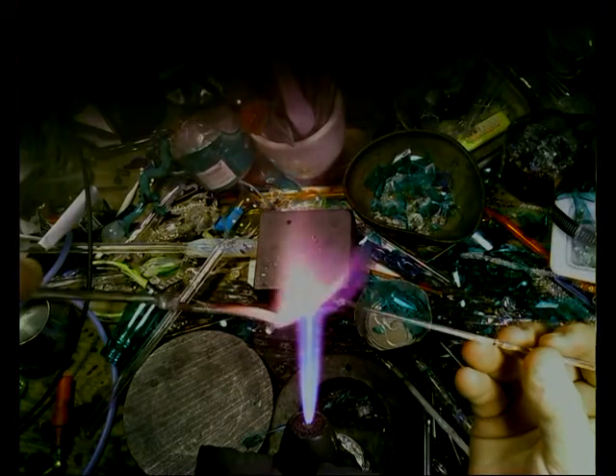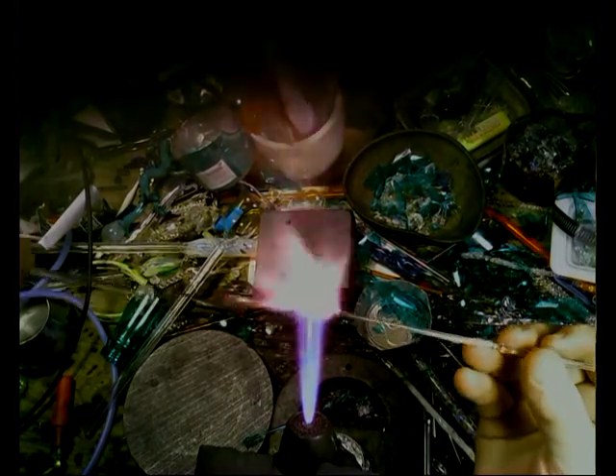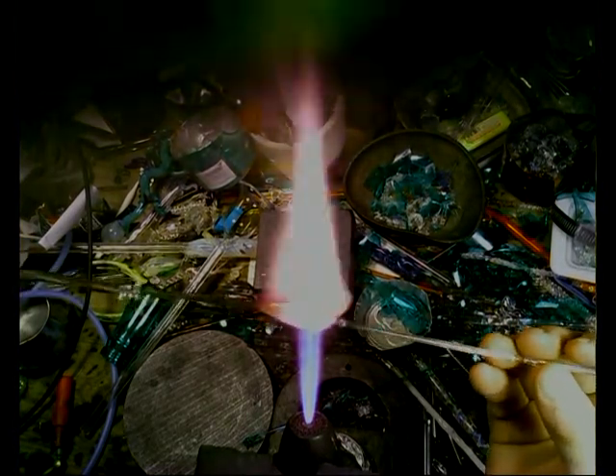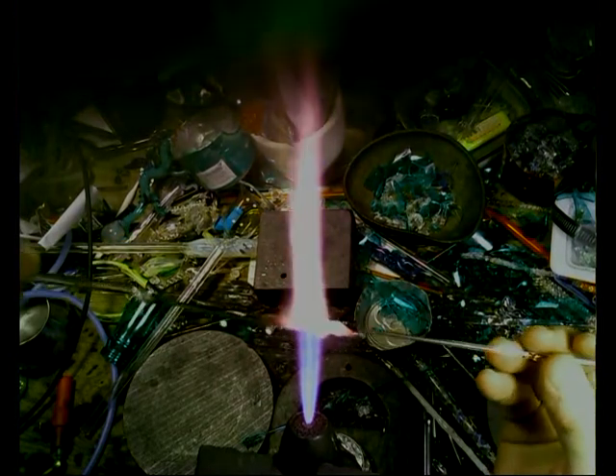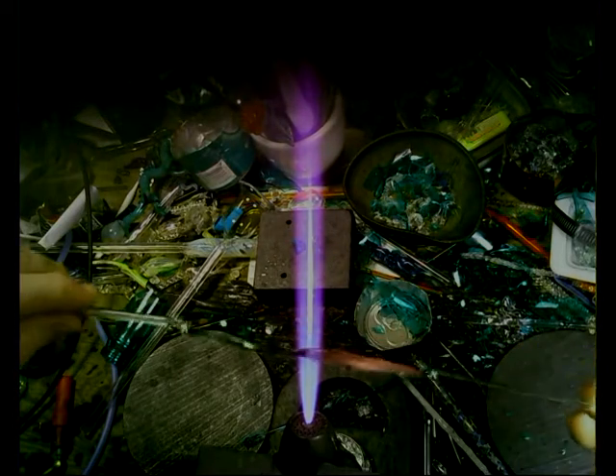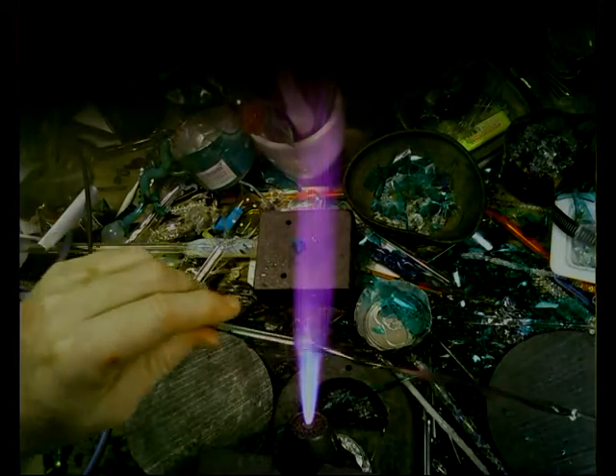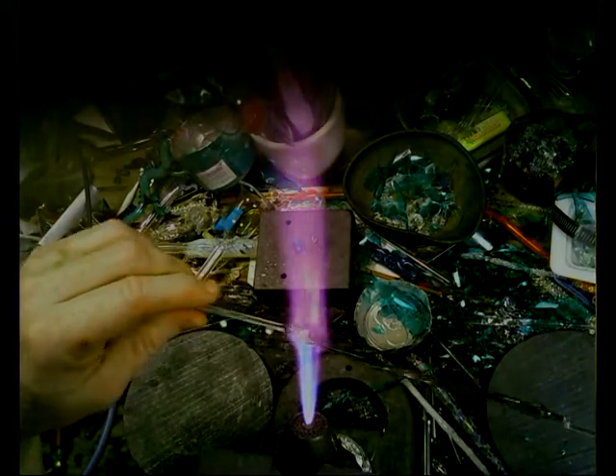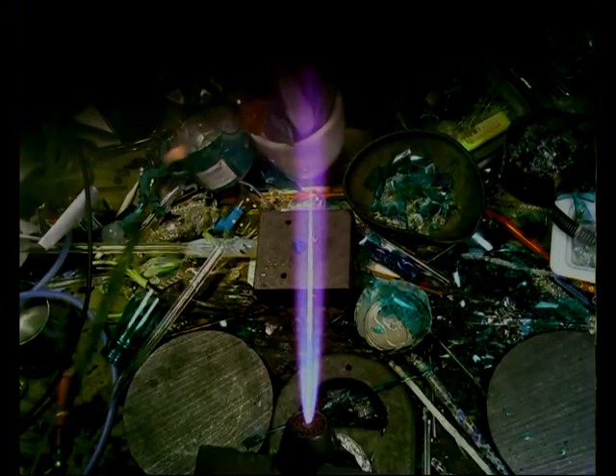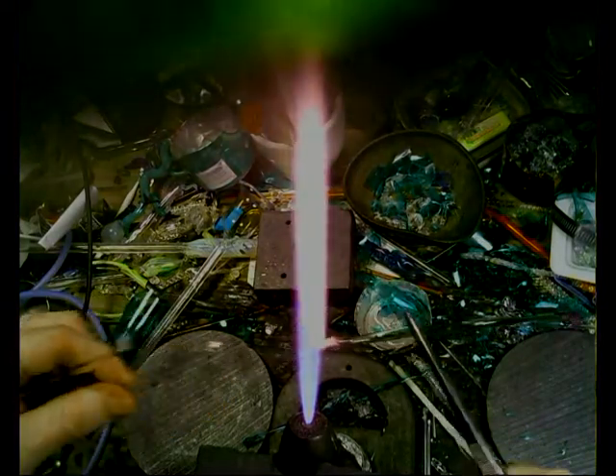And yes, you can make a lot of animals out of one soda bottle. One at a time. That's the cool thing about glass. Of course, it doesn't hurt to anneal it. And if you don't have annealing, get a can of vermiculite and warm it. Once you finish something, stick it right into the vermiculite. Let it cool at its own rate instead of at room temperature, which cools it faster. In the vermiculite, it cools at a very low rate, and more of it will be saved.